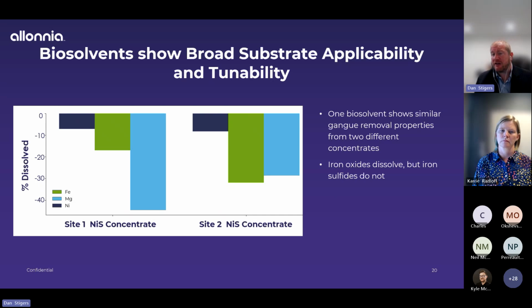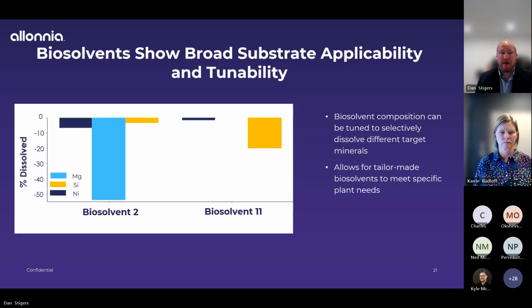And key point in here is that almost all the iron we're removing is basically iron oxide, and the iron sulfide is staying behind. Important reason is that that iron sulfide is used as a fuel when you get to the pyrometallurgical step, and it's not beneficial to remove it. What we're seeing is that our biological solvents are really just consuming the oxides, leaving the sulfides behind.